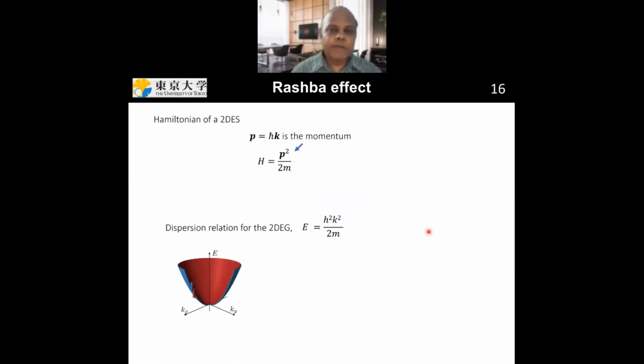So there is also another effect that is called the Rashba effect. People use it to produce spin current. At the surface or interface of materials, the inversion symmetry is broken. So whenever an electron is moving close to the surface or interface, it will experience an electric field that is perpendicular to the surface. So in the rest frame of the electrons, it translates into a magnetic field, which couples to the spin of the electron.